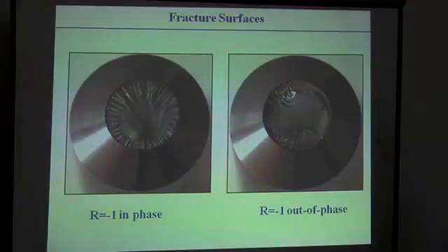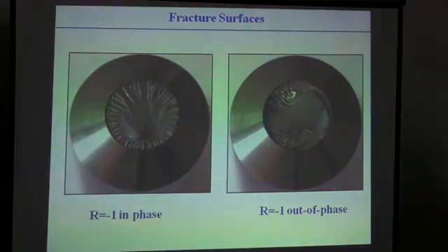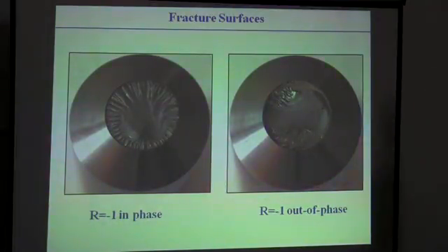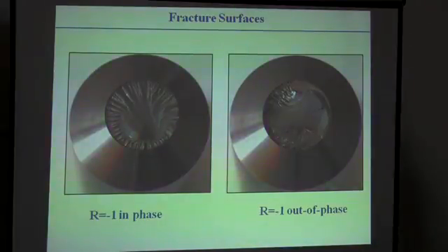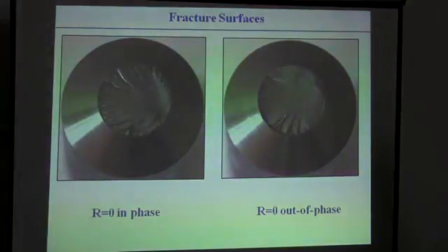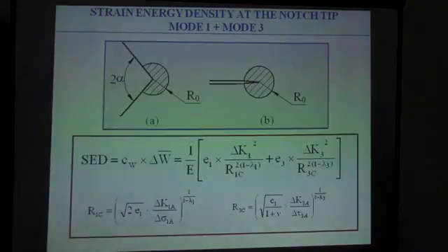After that, we have also considered the fracture surfaces of the specimens to see if there were some possible differences between in-phase and out-of-phase fracture surfaces. Yes, we have found some different behavior. For example, here there is some fretting fatigue, or a kind of debris produced by the specimen during the test, but finally this different behavior does not provoke a very strong reduction in out-of-phase loading. The same happens for the other load ratio considered. We do not have a strong difference between in-phase and out-of-phase loading. And we have applied our criterion to this material, considering the equation I have shown before.